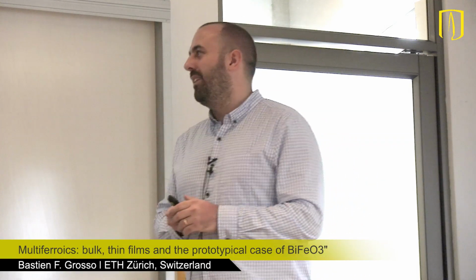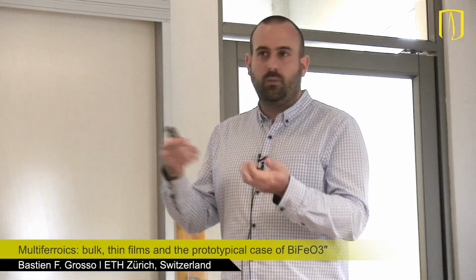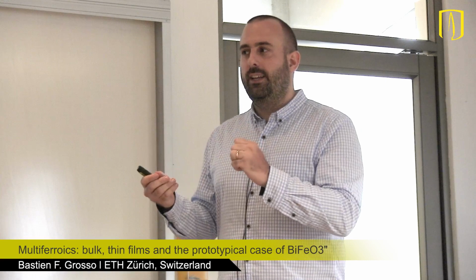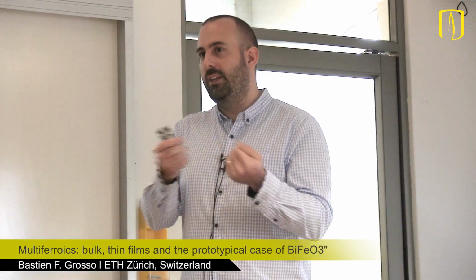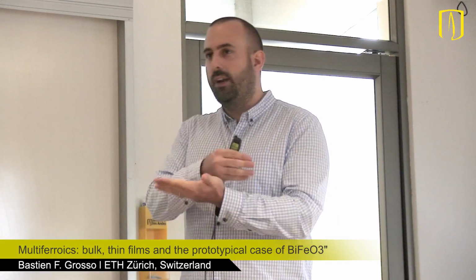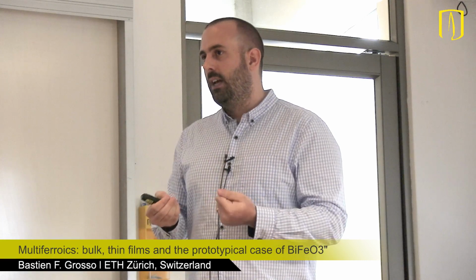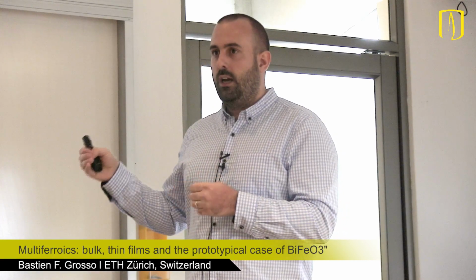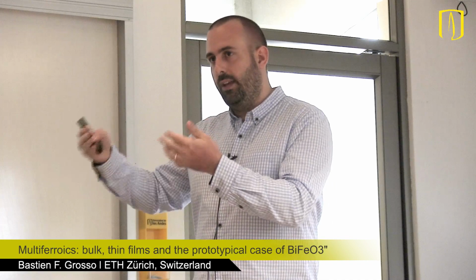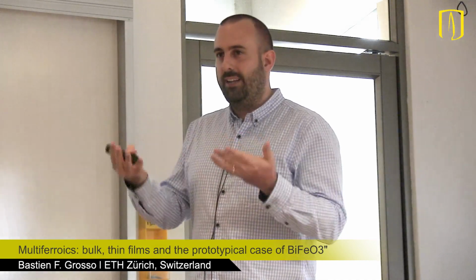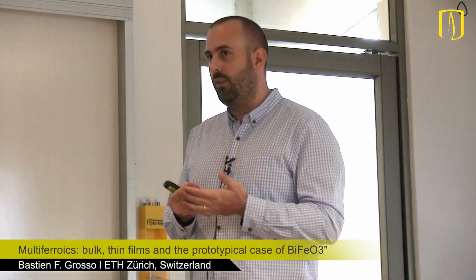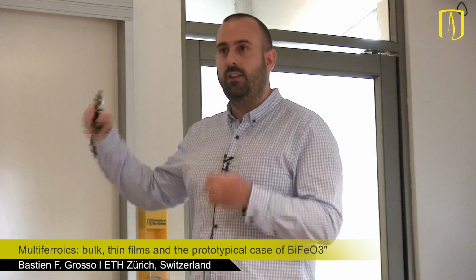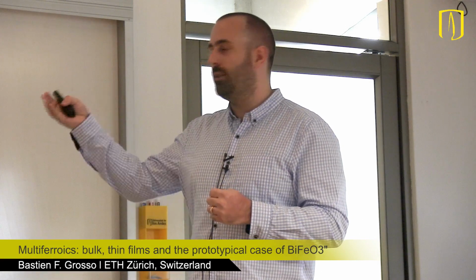¿Puedo contestar en inglés? So we studied also, because I guess your idea is it different than G-type? Could be a different magnetic order, and could there be something interesting at the interface? So from a theory point of view, according to symmetries and what could be allowed by symmetry, we didn't find that there is a different magnetic order, and from DFT it doesn't show that neither.